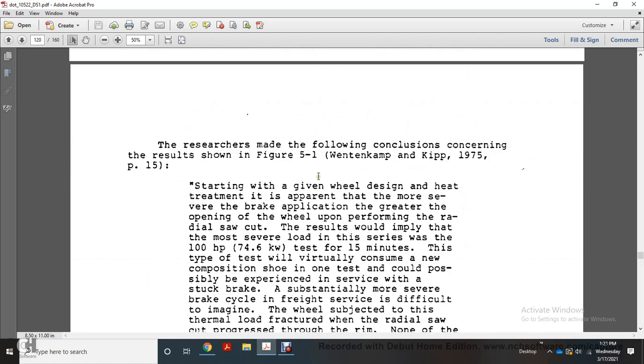Alright, the research made the following conclusions concerning the results shown in figure 5.1. Starting with the wheel design and heat treatment, the greater the brake application the greater the opening of the wheel upon performing the radial saw cut. The result implies the most severe load was the series of 100 horsepower tested at 15 miles an hour for 15 minutes.